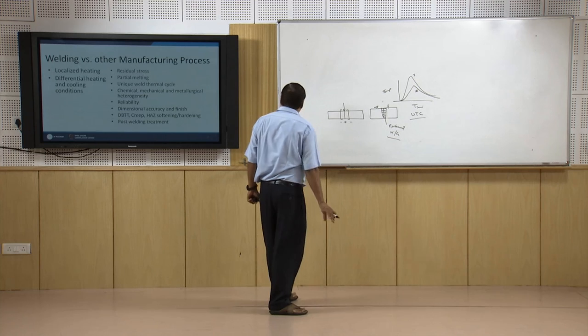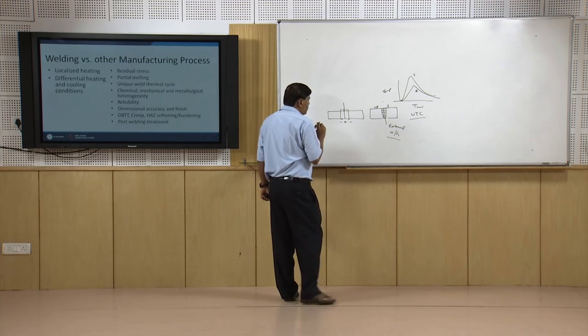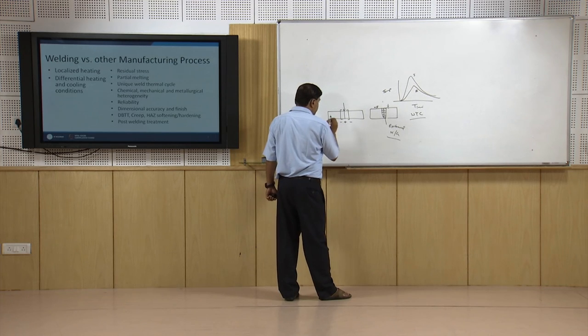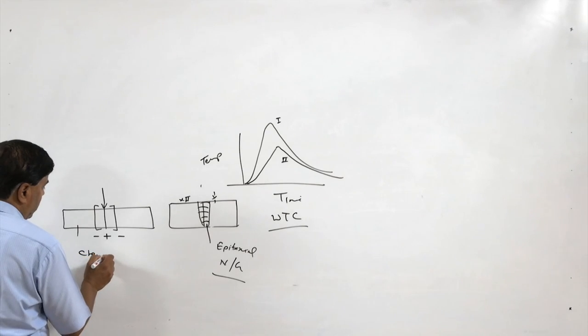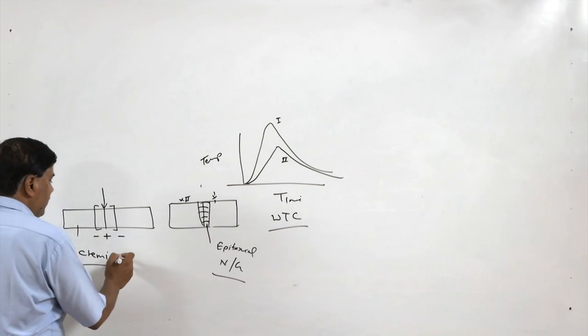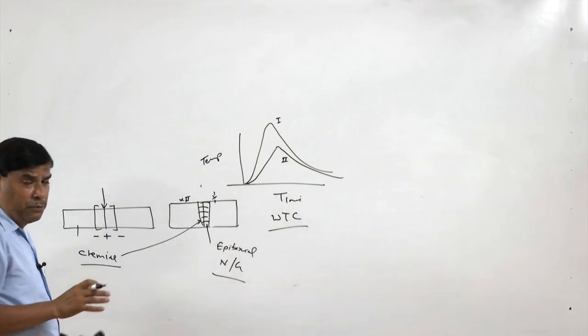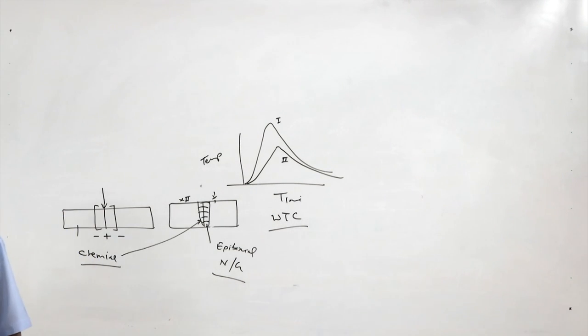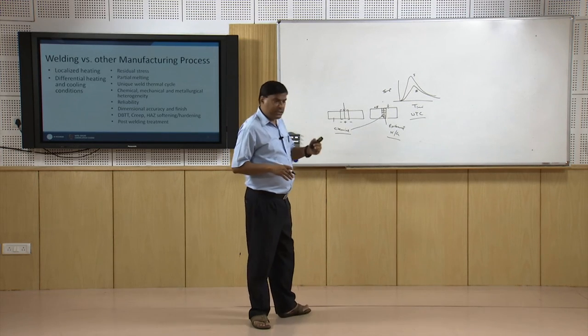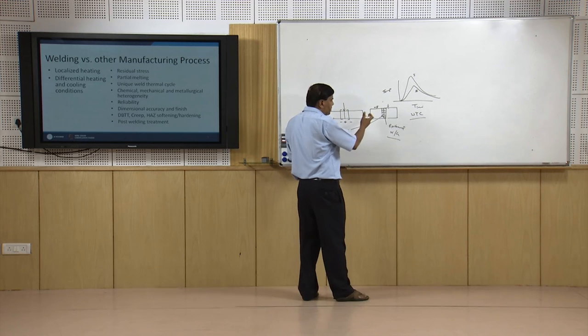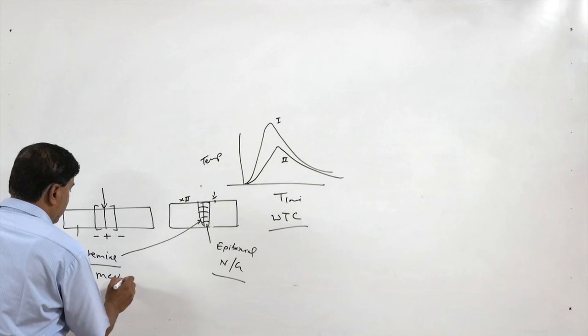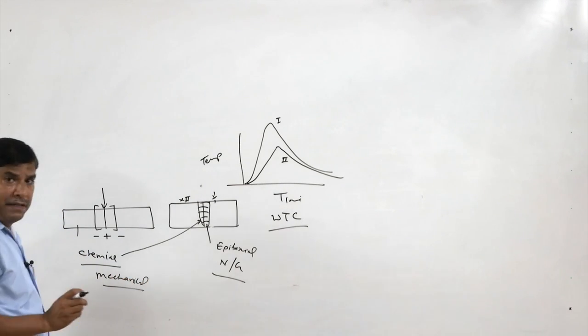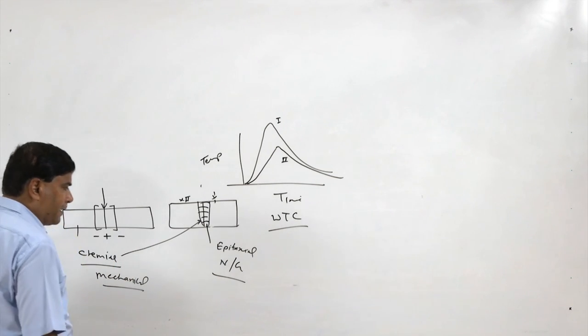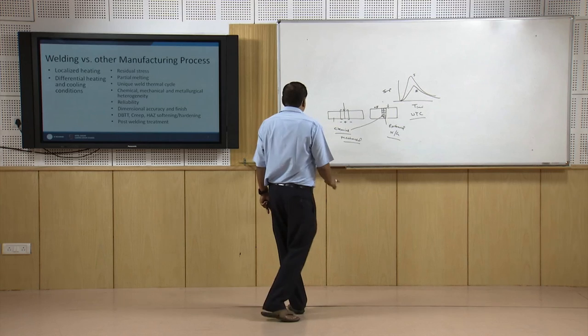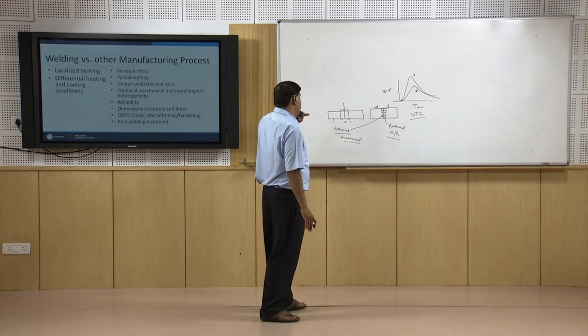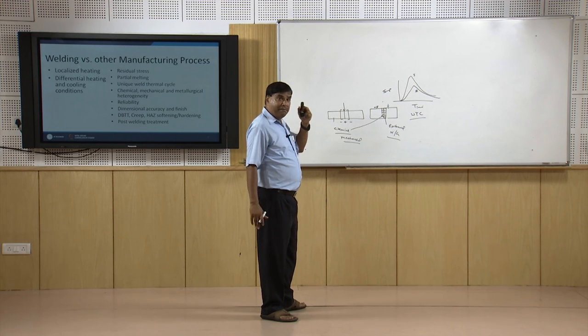Then the chemical, mechanical and metallurgical heterogeneity is another thing. Each weld joint differs in respect of these three parameters. Chemical heterogeneity: the zone which fuses offers, even of the same base metal, a different chemical composition, because some of the elements either evaporate or go with the slag after interaction with the gases in the arc environment. So the chemical composition of the weld is different, and structurally it is different. It has a typical cast structure, like a fine dendritic structure, and so the mechanical properties are different, and metallurgically the weld joint is different. So heterogeneity exists in the weld joint in terms of chemical properties, mechanical properties and metallurgical properties.